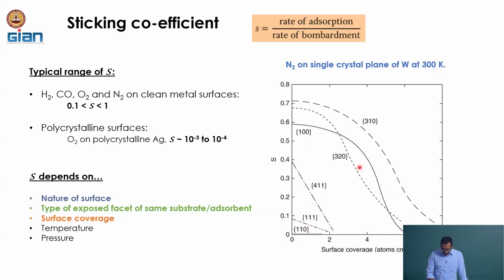But the main point from this is that even if we have the same tungsten surface, depending on the type of the facet that is exposed to the gas molecule, I can have a different amount of gas adsorbed, okay. Even for a clean surface, when there was nothing adsorbed, that is a surface coverage of 0, for different planes we saw this. What we were discussing is that the surface coverage is of course one factor that defines how much of the gases can be taken up by the surface, but most importantly what I wanted to show here is that even for the same metal, if we are exposing different facets, the sticking coefficient is going to be different, because different facets have different energetics and they are going to interact with the incoming molecule differently in general. Okay.